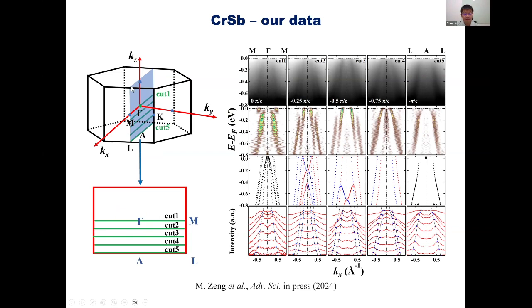In this cutting plane, we cut at five different photon energies. Also, this is an altermagnet. According to the theory of altermagnets, it has no spin splitting along gamma-M and no spin splitting along A-L, but it will have spin splitting in between these two high symmetry lines. Along gamma-M we actually don't see spin splitting here, and along L-A we also don't see spin splitting, but in between these two high symmetry lines, we see quite a clear signal of spin splitting.